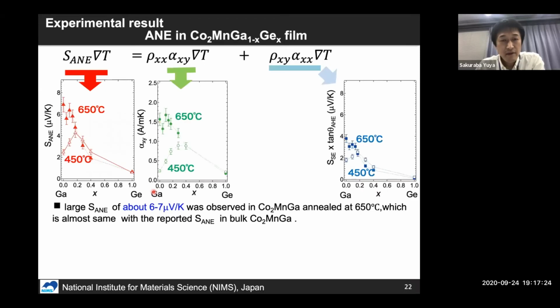And after measuring all parameters such as the Seebeck coefficient, anomalous Hall conductivity, and resistivity, finally we can evaluate the gallium germanium composition dependence of alpha XY. So as you can see, we can clearly see the drastic enhancement of alpha XY from the B2 disordered CMGG film to the L21 ordered CMGG film.